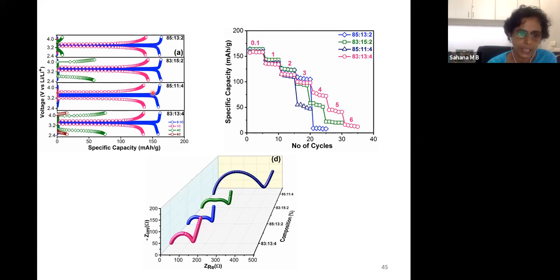You can see different charging and discharging curves of these cells. These are 4 different cells with a common active material, that is LiFePO4, but the only difference is that the electrode composition has been changed. In this case, the electrode composition is 85, whereas in this one it is 83. The blue line, the blue charging curve, is where the voltage increases during charging and decreases during discharging at a low current rate, which is done at 0.1 C.